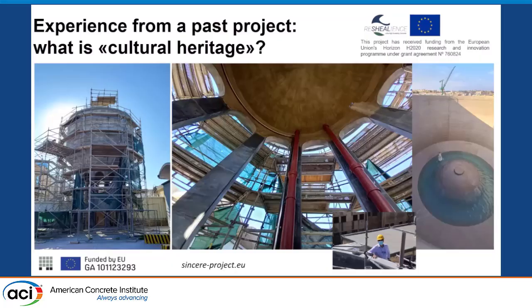As a matter of fact, the sustainability of this restoration intervention was that we used a UHPC material, so we could make the jacketing of the columns as thin as 2 centimeters, less than 1 inch, compared to a conventional jacketing, which was done in the 70s and was 7 centimeters, about 3 inches thick. So we reduced the material to less than 1/3 of what was used. So the intervention per se was sustainable because of the reduction in the volumes.